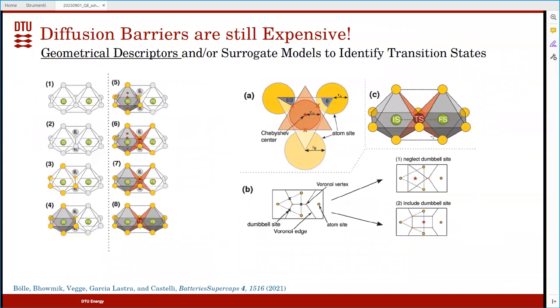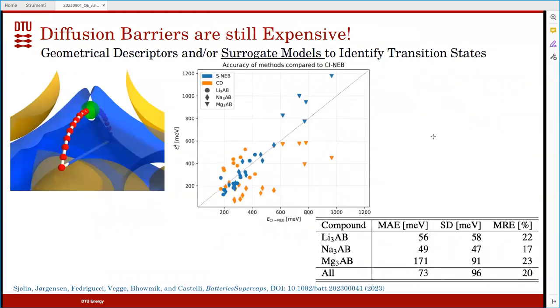We have tried also different ways to find the transition state, because if we find the transition state, then we can do the NEB with only one point. I'm not going to go into the details here, but one way was to use a geometric descriptor, in particular the Chebyshev center and Voronoi tessellation, to find the transition point and then run the NEB only on that point, or to use surrogate models. We also found that if you have a fully charged ion, then a minimum of the electron density corresponds in most cases to the transition state. So then we get that point, and from that we can just run a single image calculation.